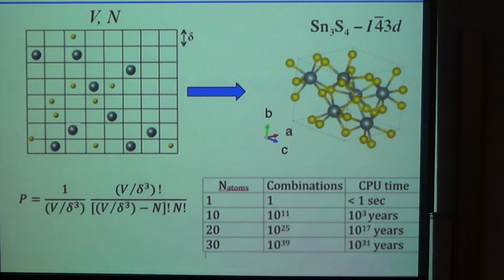So you can divide this three-dimensional space into these cubes, and you go through different combinations, different positions of the atoms, and you try to get the number of the different combinations that you can get by moving these atoms around just randomly. So if it's one atom, it's one combination, and in terms of the density functional theory calculations, it's 1 second. If you have 10 atoms, it takes 10^3 years. Go to 20, 10^17 years, and so on and so forth.